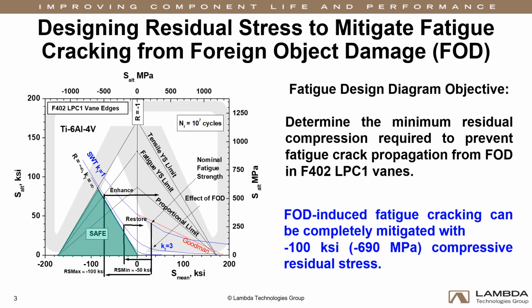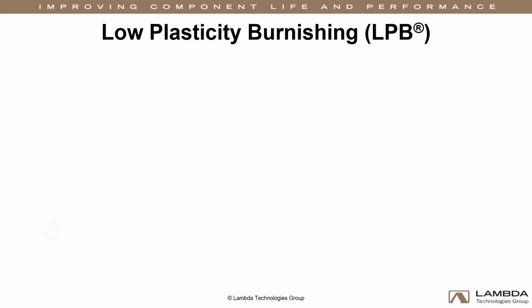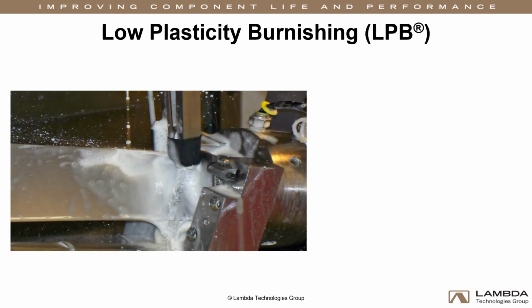In the F402 vane example, it was determined that introducing a minimum of -100 ksi, or -690 MPa, would restore nominal fatigue strength to the damaged surface. Once the engineered residual stress field is designed, the vanes are processed. We use low plasticity burnishing to introduce designed compression.